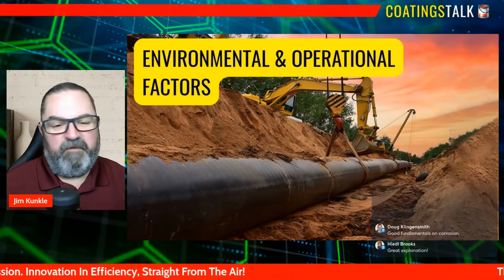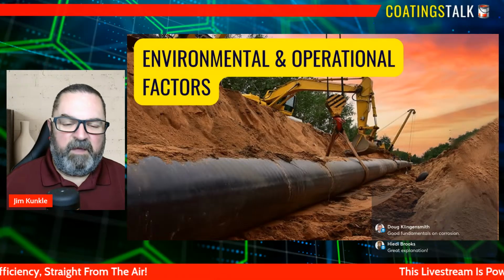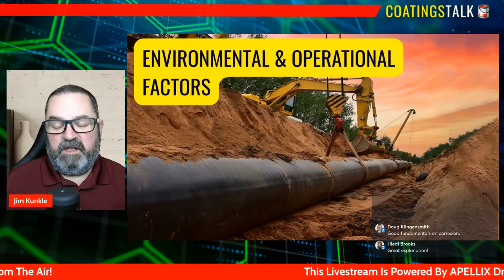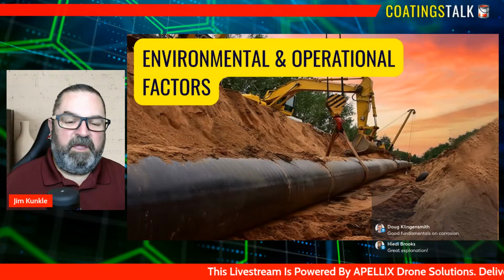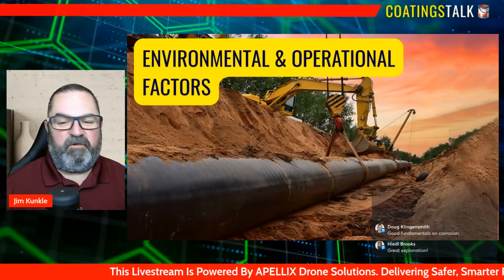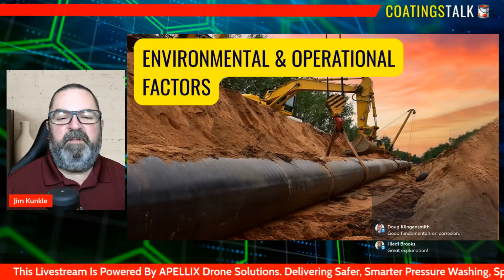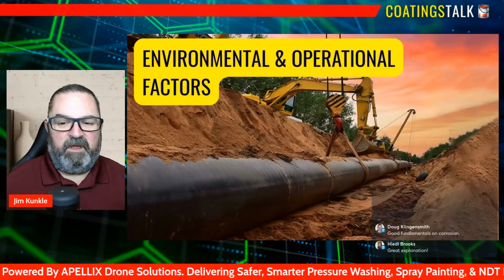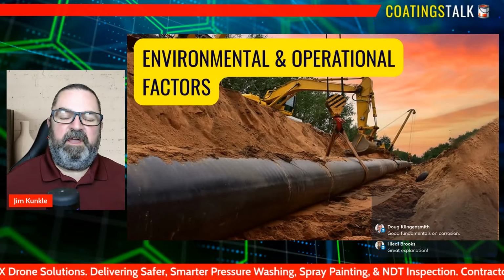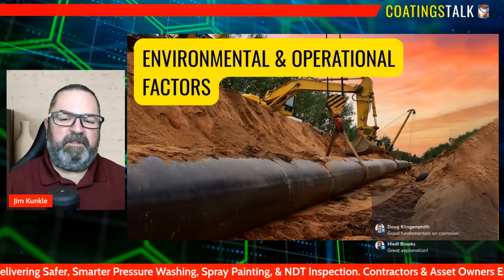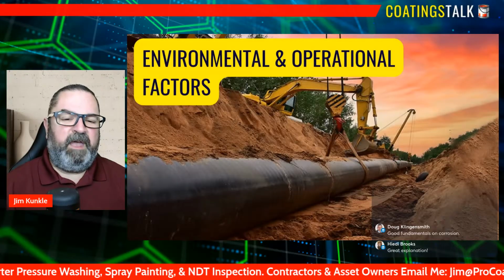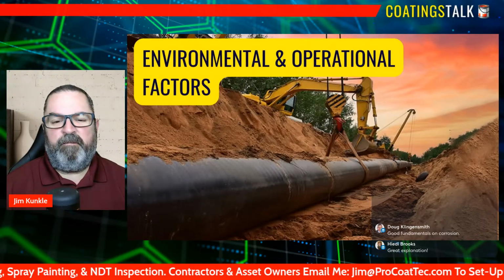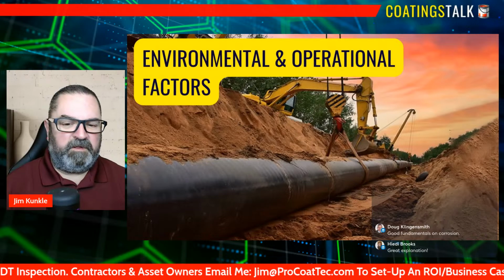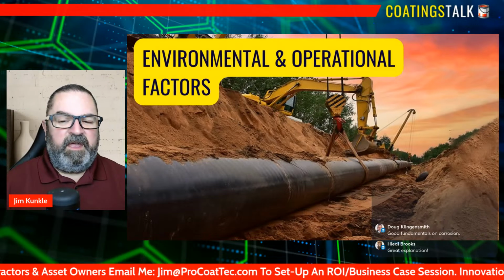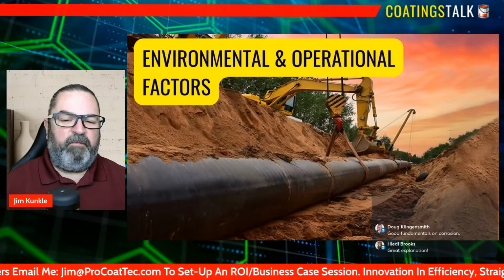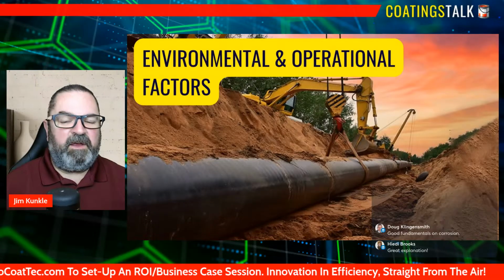Environmental and operational factors: how humidity, temperature, salt, and industrial pollutants accelerate corrosion. Humidity, temperature, salt, and industrial pollutants are some of the most influential environmental factors driving corrosion in the field. And understanding how they work gives a frontline professional a major advantage. High humidity increases the amount of moisture available on metal surfaces, creating a thin, invisible film of water that enables the electrochemical reactions behind corrosion.